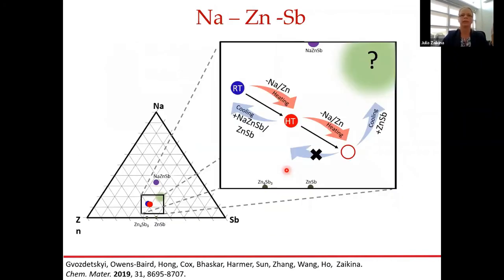So basically, if you want to represent this with our compositional diagram, we start with the 143 room temperature phase. Upon heating, there is some sodium and zinc elimination, so we get to that high temperature phase. And then if we start here with a composition which is already deficient in sodium and zinc, further heating allows us to shift the composition toward even less sodium and zinc. So with this composition here, we haven't tried synthetically, but we get to it by heating.